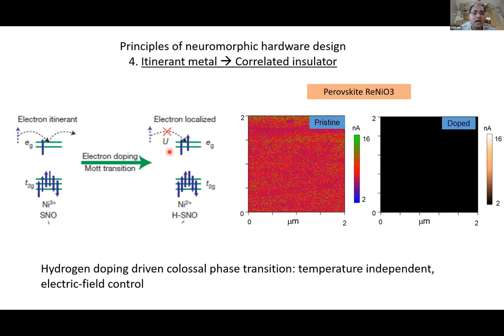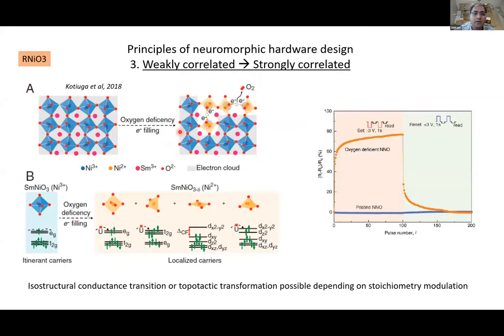Whereas if you are already starting with a heavily insulating compound, then you have to go to this type of argument where you're already starting with the correlated system, but you're changing the strength of the correlation. And so this is also possible. Again, here entirely, we can do this with oxygen. What we find is the dynamics are different, but in terms of just near DC type measurements, you can do pretty much the same level of basic research in terms of understanding the physics of what's going on.